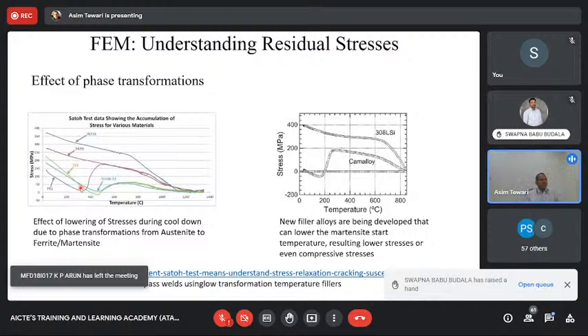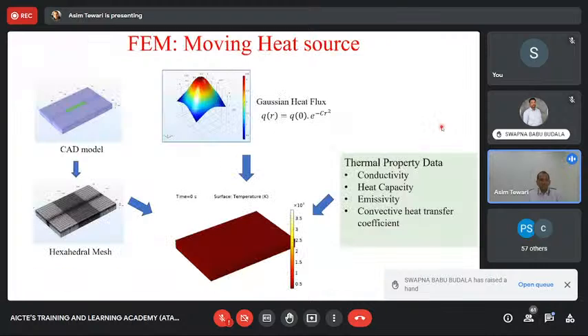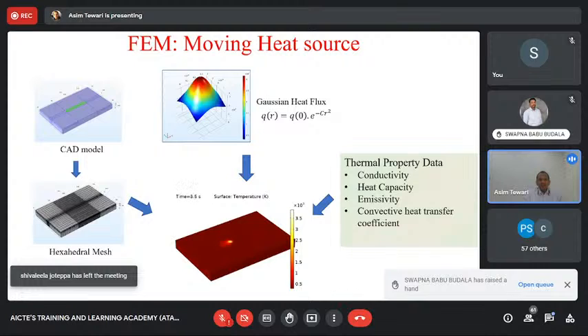Now, what you need to realize, and I'll just take you to the next slide, is that this entire process has one-sided coupling from the heat transfer model to the solid mechanics model. But the solid mechanics model is also being coupled with the phase transformation model. When you have austenite formation, there's a volumetric change. When there is a martensite formation, there's a volumetric change. And these volumetric changes will create eigenstrains leading to residual stresses. So you need to model them at the same time. Now let me quickly show you the complexity which comes because of the phase transformation modeling.